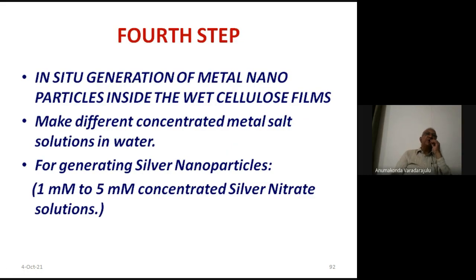In the fourth step, we have to in situ generate the metal nanoparticles. For that, we have to prepare the required salt solution. Suppose if we want to generate silver particles, take silver nitrate in water, because it is water soluble. So in water at different concentrations, 1 millimole to 5 millimole concentrations, and in each solution, you dip this matrix film. Matrix film is nothing but the cellulose along with this infused leaf extract.